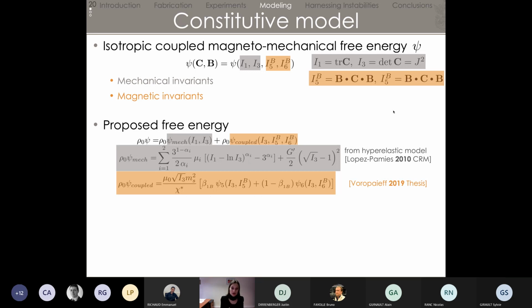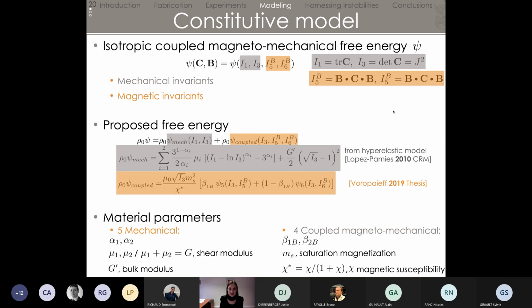This free energy is separated in a purely mechanical part, which means if you don't have a magnetic field applied, the orange part goes to 0. And you have, for the mechanical behavior, a hyperelastic model from Lopez-Pamies, proposed by Oscar. Now, if you switch on the magnetic field, you have a free energy that's coupled in the sense that inside your equation, you have I3, a mechanical invariant, as well as the magnetic invariant. So the whole game was to propose a shape for this function. I won't go deeper into it, but at the end of the day, we have classical mechanical parameters to find, which are the ones from the Lopez-Pamies model, and 4 coupled magneto-mechanical parameters.